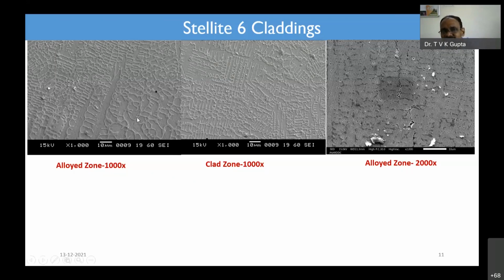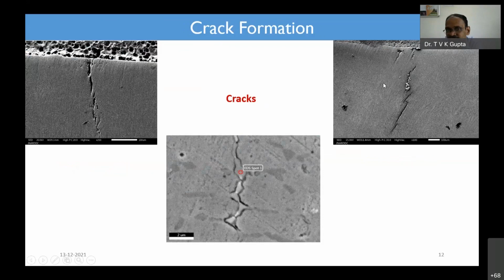If you look at the SEM of the laser cladding of Stellite 6, this is the alloyed zone. This is the clad zone. This is again the alloyed zone. But at very high powers, what we have observed is cracks. This is not allowed, because the process itself is prone to cracks. So again we restarted our work, trying to optimize it so that there should not be any cracks. In order to avoid cracks, we need to reduce the thermal difference between the substrate and the clad. How can you reduce that?